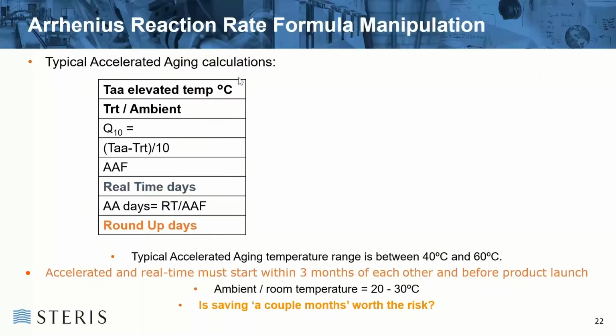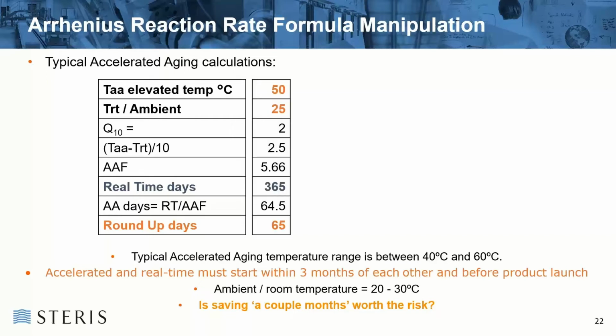So typically we're looking at an accelerated aging calculation. From the actual formula, you can manipulate what you're actually doing. Say if we take an example, an elevated temperature of 50 degrees with a 25 degree ambient and a Q10 value of 2, 365 days can be done with an accelerated aging in 65 days. So it's a huge saving in the introduction of your product.